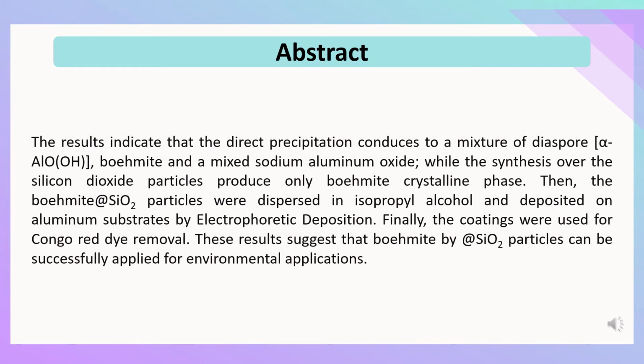The results indicate that direct precipitation leads to a mix of diaspore, boehmite, and a mixed sodium aluminum oxide, while the synthesis over the silicon dioxide particles produces only the boehmite crystal phase. Then, the boehmite and silicon dioxide particles were dispersed in isopropyl alcohol and deposited on an aluminum substrate by electrophoretic deposition. Finally, the coatings were used for Congo red dye removal. This result suggests that boehmite on silicon dioxide particles can be successfully applied for environmental applications.